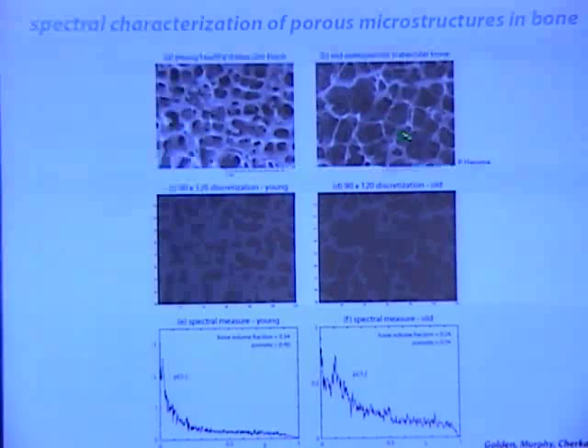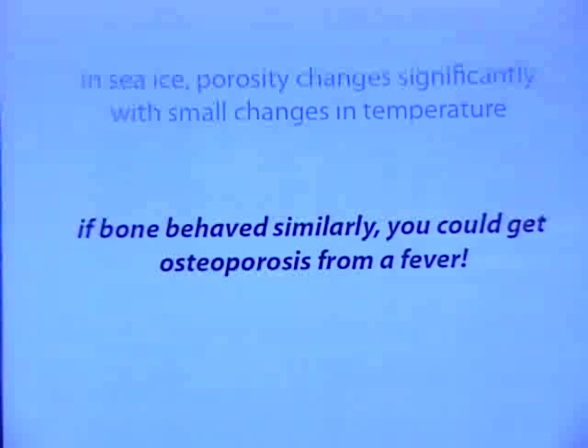Here's healthy bone, osteoporotic bone, and you see these differences in the spectral measure. In sea ice, the porosity changes significantly with small changes in temperature, and if bone behaves similarly, you could just get osteoporosis from a fever or a flu.